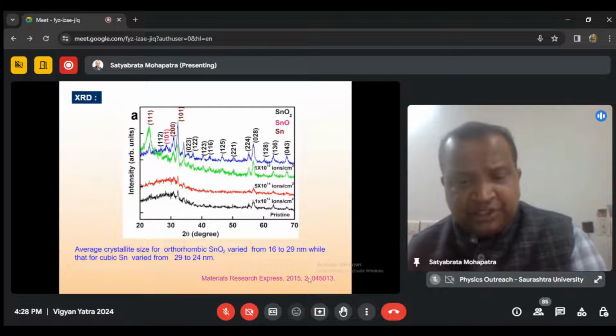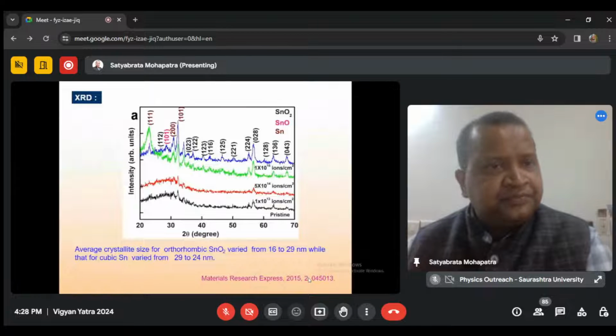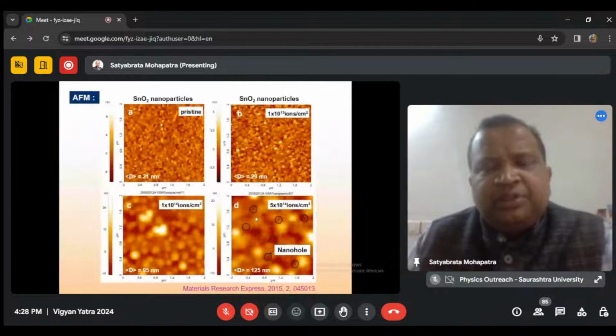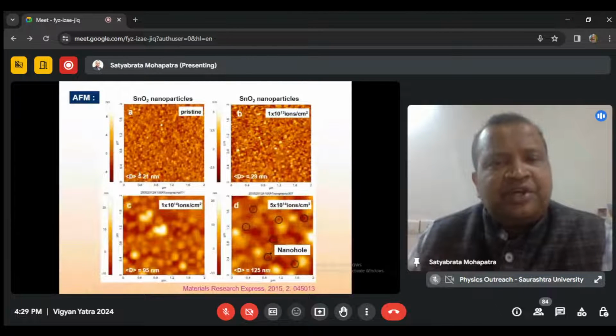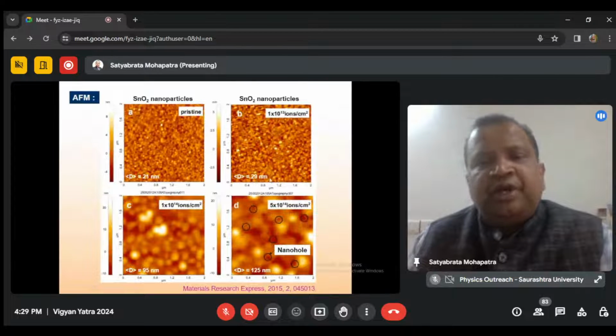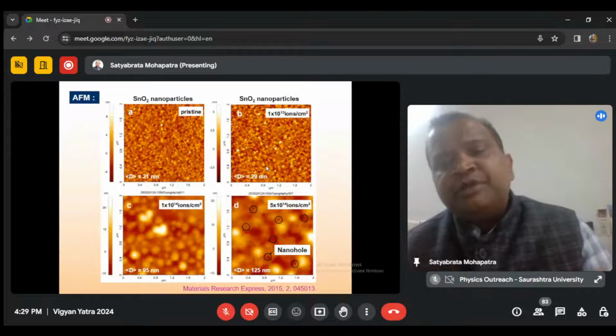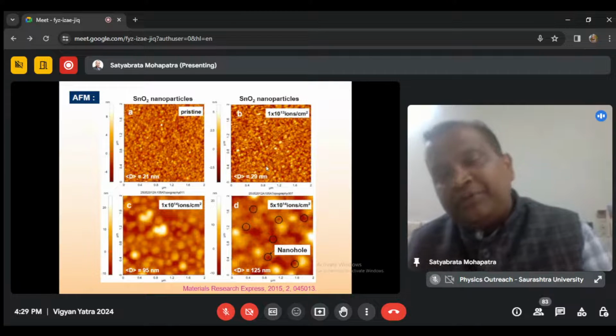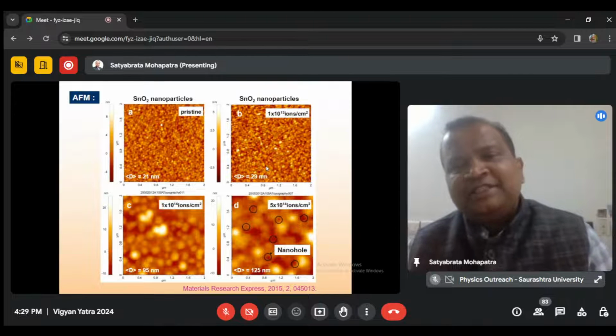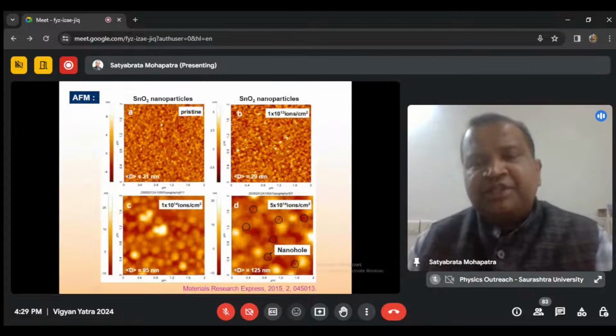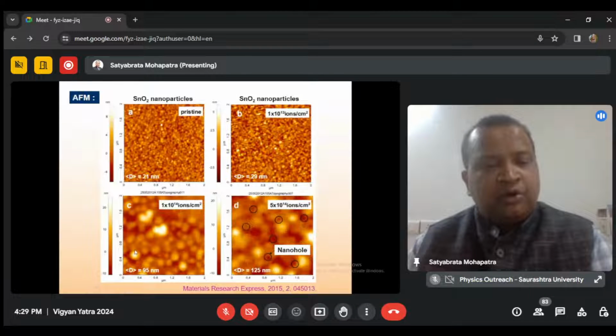This work came in 2015 in Materials Research Express, again from Neha Bharat's thesis. You can see that tin oxide nanoparticles were there in 21 nanometer average size in the crystalline film, which on irradiation grew to a size of 29 nanometer by the simple conventional Ostwald ripening process, which is very clear when you expose a nanoparticle system to an energetic ion beam. In this case, we are using electronic excitations because the film thickness is very small compared to the ion range. So when you excite this nanoparticle film, there will be growth of nanoparticle size. That's the first response. When you increase the ion fluence further to 1 × 10^14 ions per centimeter square, there are dome-like structures with average size 95 nanometers. So from 21 to 95, there is a clean growth of nanoparticle size.